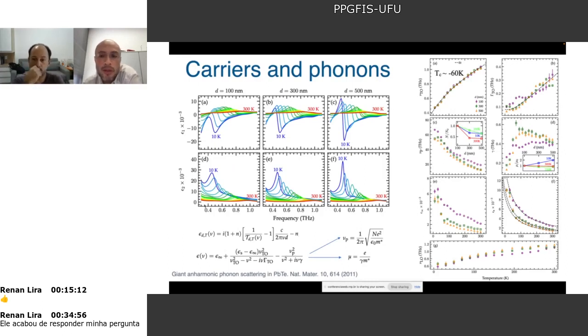And at this point, I think it is very nice to show you the capability of this technique. We can calculate the fitting here. We can obtain the frequency of the phonon, but also the plasma frequency. And from the plasma frequency, we can obtain the sample concentration if you know the effective mass. So here you can also obtain the concentration of the film, and from the width, from this gamma, you can obtain also the mobility of carriers.